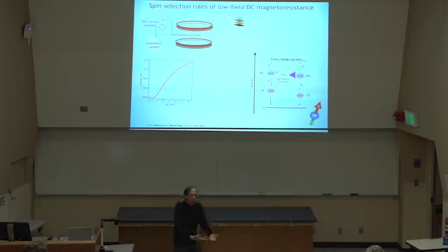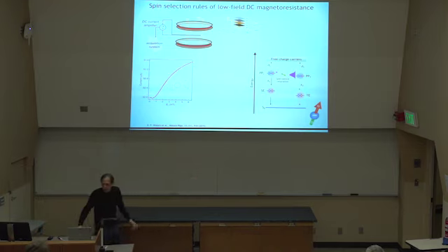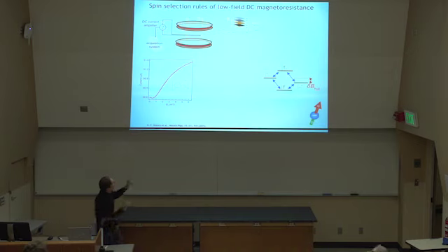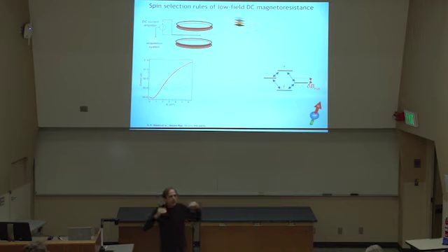And that means in the steady state, you simply pump triplet states. You create, of course, as many states with triplet content as states with singlet content, and you pump them to higher and higher densities, but the singlets get flushed out and you're stuck with triplets. So you pump triplets just by turning on this device. And what now happens when you change the magnetic field is, all you do is you essentially change your externally applied magnetic field that slightly shifts these levels, and these levels now compete with local hyperfine fields. These are local magnetic fields in these materials.